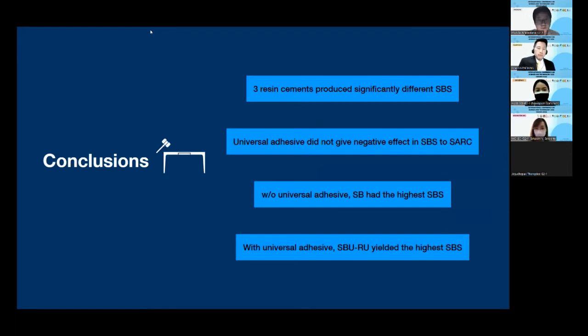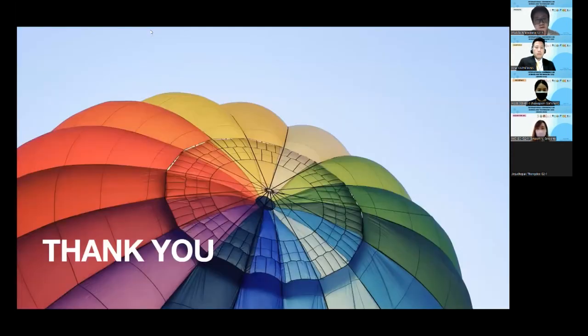Here is the conclusion. Three resin cements had significantly different shear bond strength in this study, and coating with universal adhesive did not give a negative effect to self-adhesive resin cement, but one group showed a positive effect, as Single Bond Universal combined with Rely X U200 yielded the highest shear bond strength in this study. But without adhesive pretreatment, Superbond showed the highest shear bond strength. Thank you.